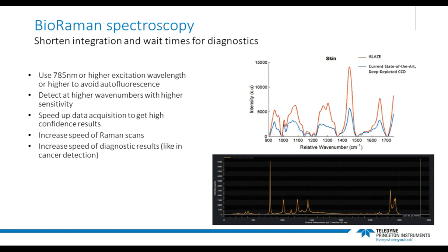So the first application example I chose is bio-Raman spectroscopy. In bio-Raman, you typically excite with wavelengths of 785 nanometers or even higher wavelengths. So the Raman signal you measure stretches deep into the NIR. And the reason to use these high excitation wavelengths is typically to avoid autofluorescence that happens in tissue, and that really overwhelms the really weak Raman signal for lower excitation energies.